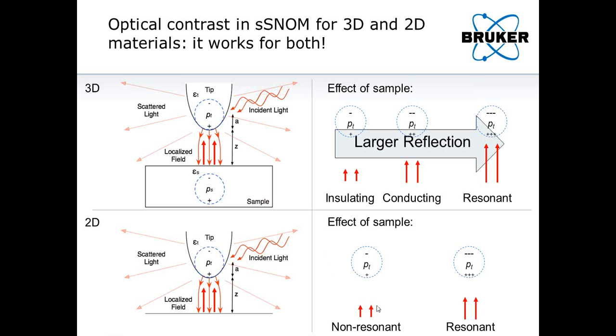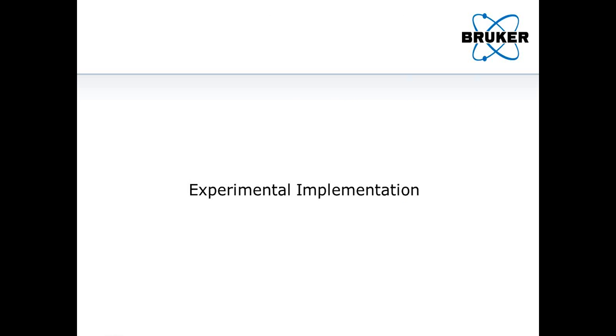For a 2D material, I break it up into two categories: non-resonant and resonant. By resonant, I'm talking primarily about plasmon resonances, such as I'll show later in graphene. If you have a plasmon resonance, you'll have a much larger reflection of evanescent waves back to the tip, causing a much larger tip dipole and therefore a larger amount of scattered light detectable in the far field. That summarizes the effect of the sample on the tip dipole.